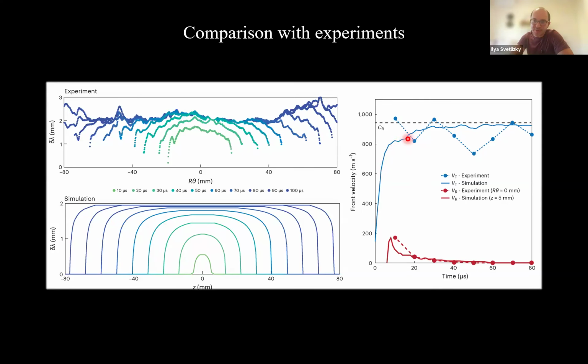But this is the transverse direction, right? So I think the idea is that the radial expansion of the crack is still within the cohesive zone. So when the crack finishes the jump, it's still within the cohesive zone size. And while you're absolutely right that in the transverse direction you can assume that you run out, the crack itself is still within the cohesive zone.